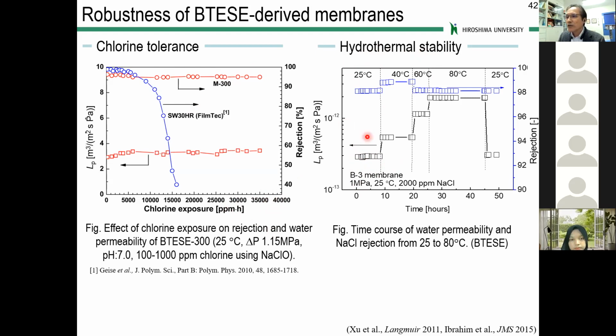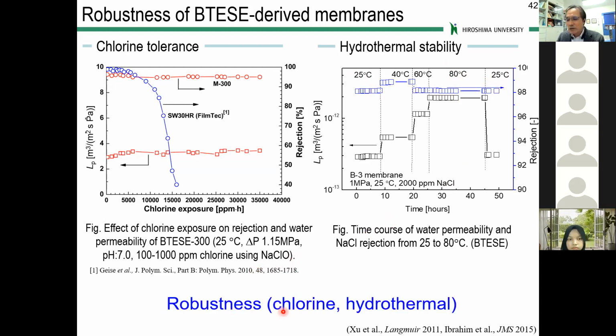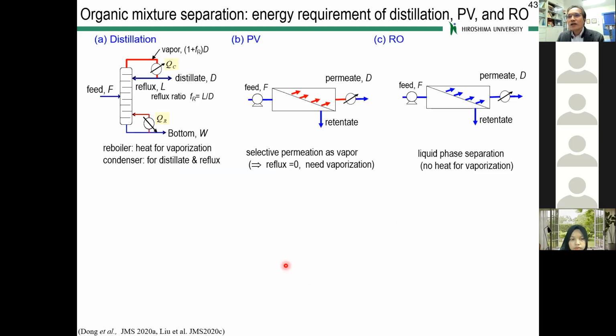Okay, the experiment was started from 25, and then temperature was increased to 40, 60, 80, and then back to 25 degrees C. You can see almost similar water permeance at 25 degrees C, even after 80 degrees C for several tens of hours, and the rejection was kept. So this indicates our membrane is robust to chlorine and high temperature hydrothermal conditions. Now this membrane was used for aqueous systems. Now I try to extend this type of membranes to organic mixture separations.